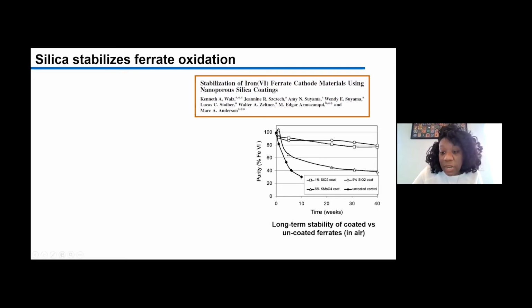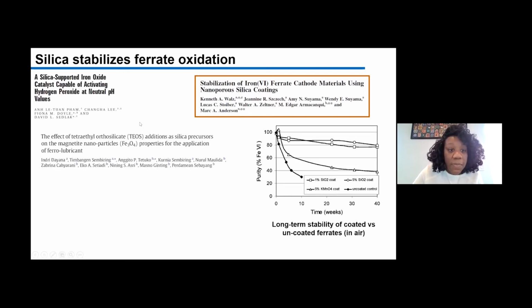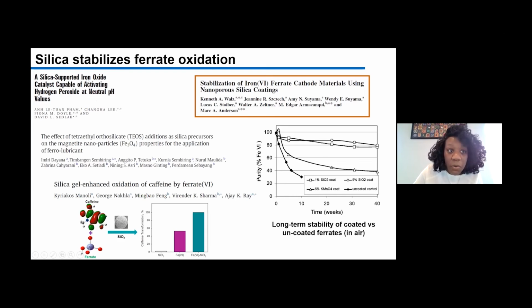So in this study, which was done in air, they exposed ferrate to a silica coating and found reactivity on the order of weeks as opposed to days for their unmodified or uncoated ferrate reactivity. Some other studies, again, suggest that the presence of a silica-supported ferrate was really beneficial to enhance and prolong its reactivity. So here, this study is showing the addition of silica gel to a ferrate in solution resulted in very high, basically 100% transformation of caffeine, which is a nice wastewater and stormwater indicator compound.